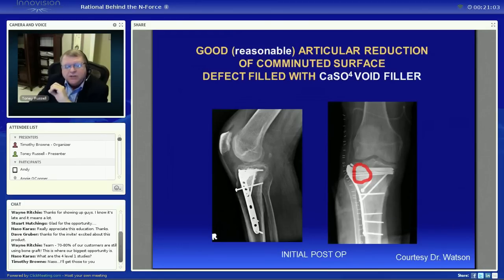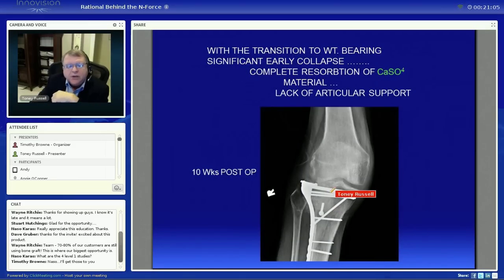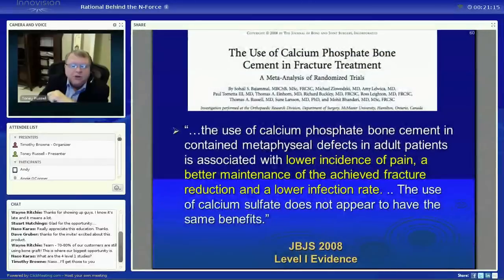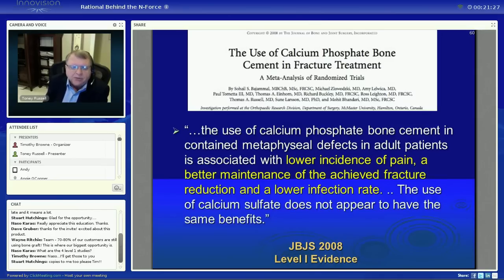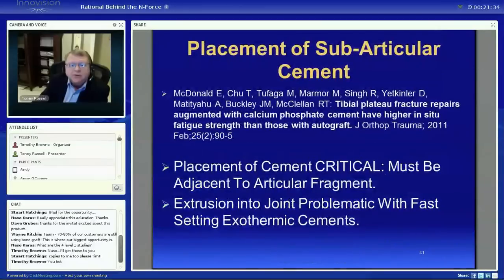The trouble is calcium sulfate is a salt. And so what it does, it just dissolves away. So at 10 weeks, the cement dissolved away and the whole articular reduction collapsed. So the calcium sulfates are not strong enough to hold this reduction. And this was done in a meta-analysis study that we published, again, 2008, and showed that calcium phosphate cement, not the calcium sulfate, had better fracture reduction maintained and lower incidence of pain. So again, level 1 evidence that these guys should be changing to the ceramic cements.